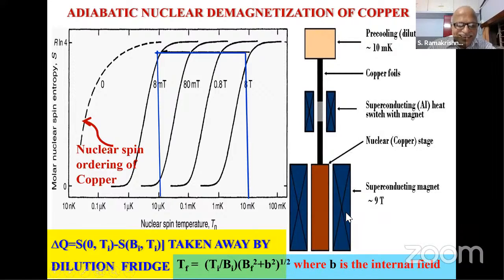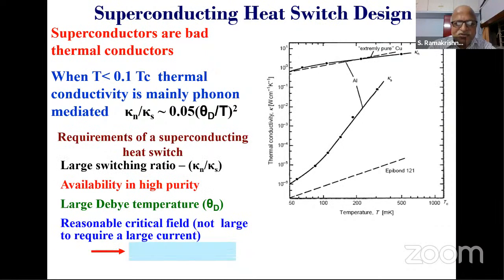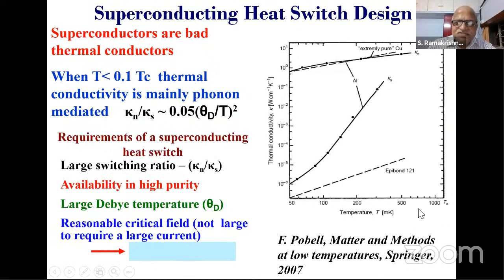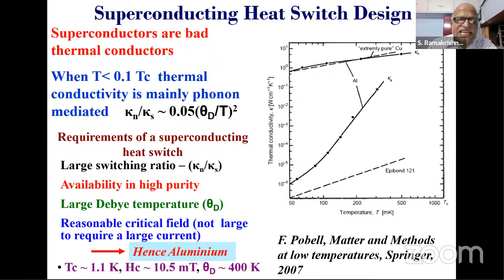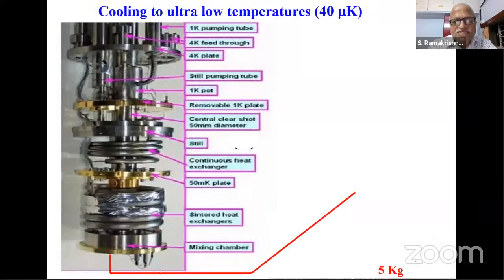So you can simply reduce the field slowly, and you can do an adiabatic demagnetization and reach very low temperature. In our case, we reach about, so this is just to tell you how it is done. You know, the thermal conductivity of a superconductor, you see aluminium, is coming very close to a polymer at low temperatures. It is as bad a thermal conductor as this epibond, which is the insulating polymer. Basically, because the thermal conduction from the normal electrons is reduced as they go into a superconducting state. So we will come to this part a little later. So a superconductor can be used as an excellent thermal switch, and that's what we do in a dilution refrigerator.